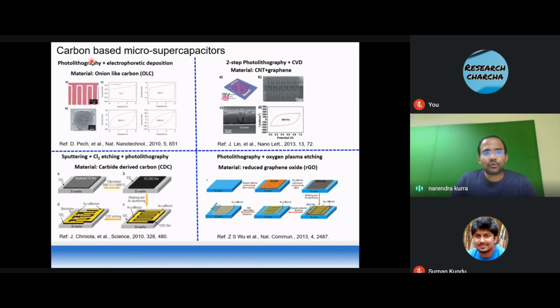Let me run through some of the very early reports on micro supercapacitors. In fact, those are the triggering points for many more discoveries and studies laid out in the literature on micro supercapacitors. So the two key publications came in 2010, exploring carbon-based materials. This is onion-like carbon, whose typical diameter is around 10 nanometers. The photolithography technique was used to make interdigitated gold electrodes, followed by electrophoretic deposition. These are charged particles, so they can be attracted selectively to the metal fingers.